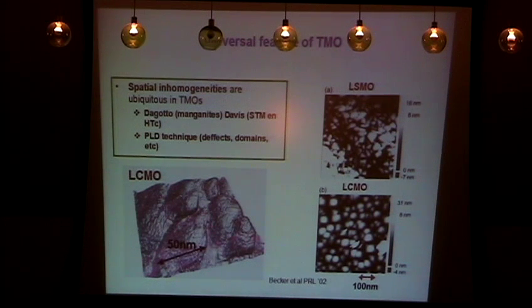It can be driven by the way you fabricate them, but even if you try to make samples which are very well controlled, there is always some degree of phase separation that occurs even at the electronic level. That's why these systems have a wide variety of ground states that can be tuned with temperature and composition. They are very subtle systems. So you can tune them through metal-insulator transitions, and that's why the most studied systems in the past 20 or 30 years are the cuprates and the manganites, which are the hallmark of the transition metal oxides.